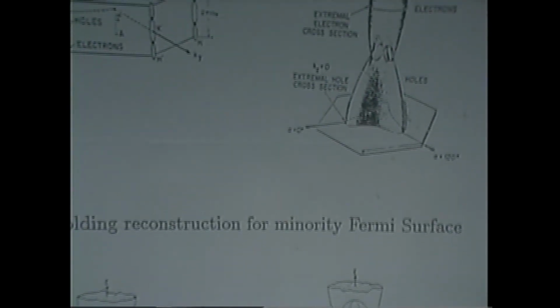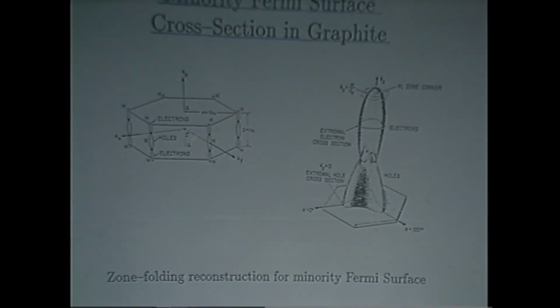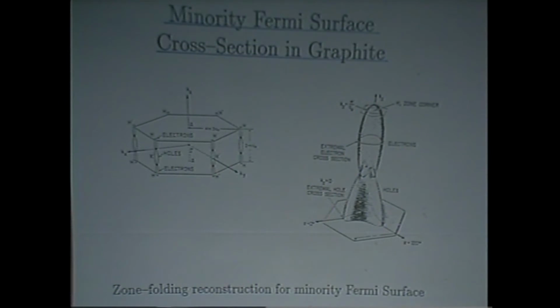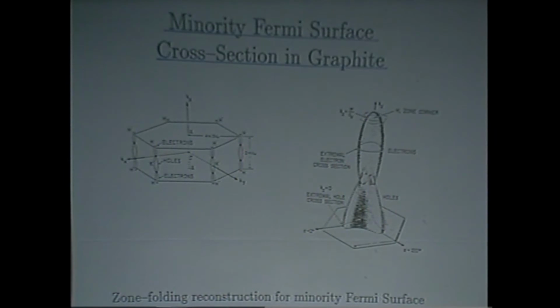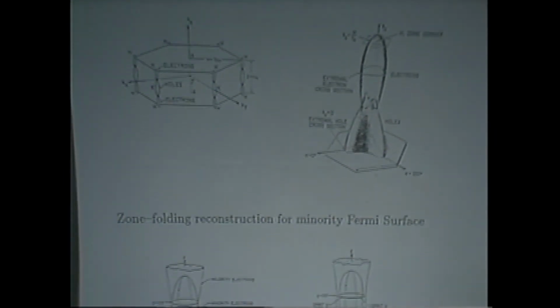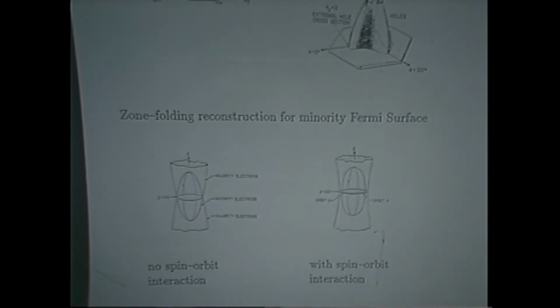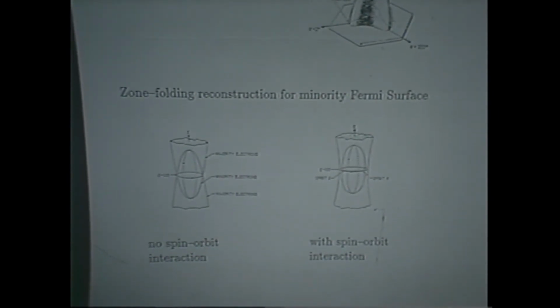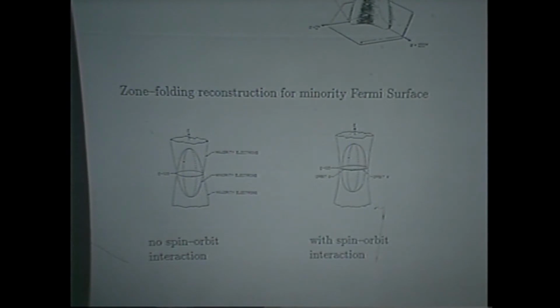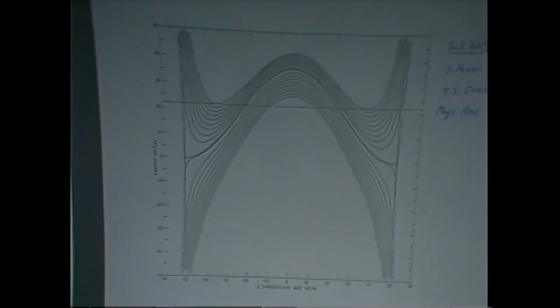Well, if you look at the extremal cross-section, you see a little piece of the Fermi surface protruding over the zone boundary. And then if we translate this piece down below by a reciprocal lattice vector, we can join them up and we get this football-shaped thing, and that's the minority surface in graphite. So we could explain this cross-section at the zone boundary with that interpretation. We had another interpretation that we liked better. This is an interpretation that everybody knows today. It's in all the textbooks. Everybody uses it. But at the time we did this, it wasn't all that common.